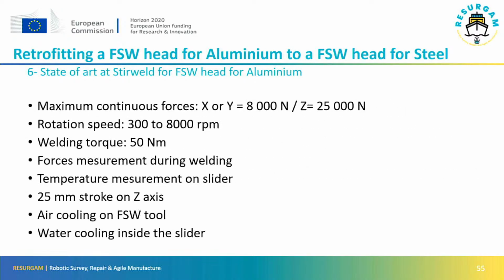So on the actual FSW head, these are the specifications of the product. The main force that will be interesting in the FSW process would be the force on the Z-axis, so the forge force, and the force on the X and Y axis is proportional to the Z forces. Actually, the force on the Z-axis is about 25 kilonewtons. The rotation speed goes up to 8,000 RPM, and the torque goes around 50 Newton meters. We have a temperature measurement on the slider part, and the stroke of these sliders is about 25 millimeters.